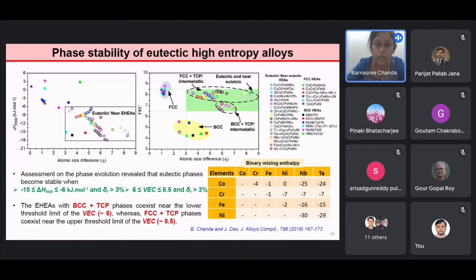Another important parameter is the valence electron concentration for the phase stability, and when we compare it with the BCC and FCC high entropy alloys, we see that in the range of 6 to 8.5, the eutectic and near eutectic high entropy alloys are stable. Another important conclusion that can be drawn from this plot is that in the upper limit of the valence electron concentration, all the phases consist of FCC and intermetallic phase, and in the lower region, it consists of BCC or topologically close pack or the intermetallic phase. Therefore, not only will we get a prior idea of the phases present, but we may also predict the mechanical properties from this plot.